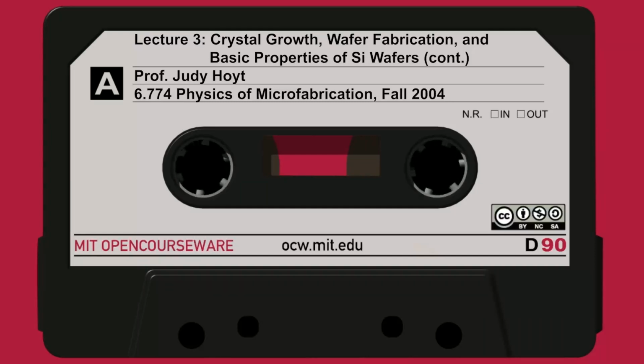Slide 29, we'll continue this in more detail next time, but I talk about wafer cleaning. We do introduce onto the wafer a certain amount of impurities ourselves. In the photolithography process, remember, that organic material, photoresist, it turns out, is a contaminant. But we have to use it because it does photolithography, and we have to remove it every step because we certainly don't want it on the wafer when we're doing any high temperature processing. So after we do resist strip, we typically then have to clean the wafer using a special clean that we'll talk about next time, RCA clean, and then we do the process step.